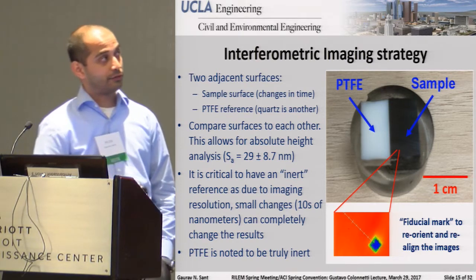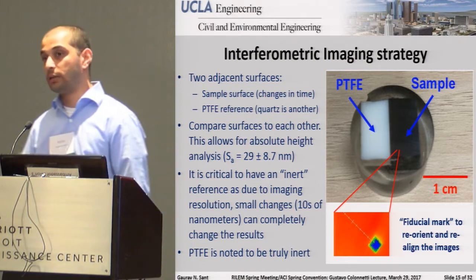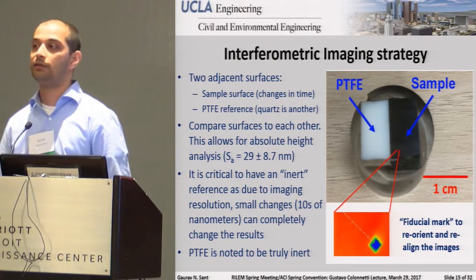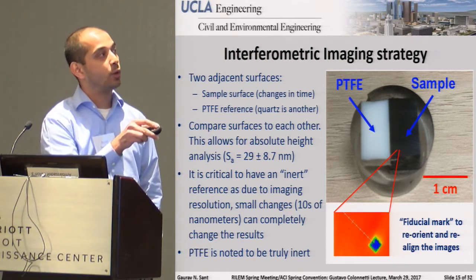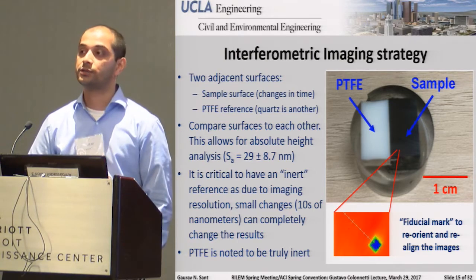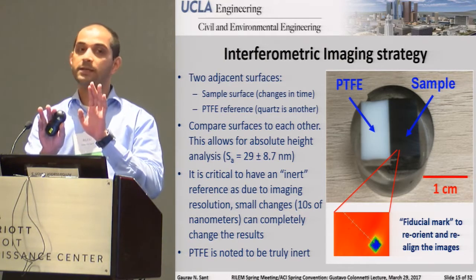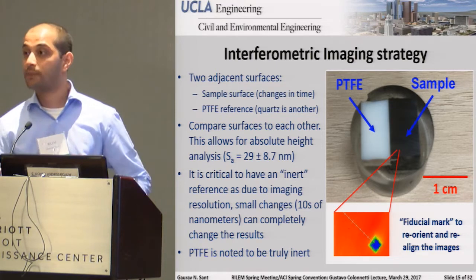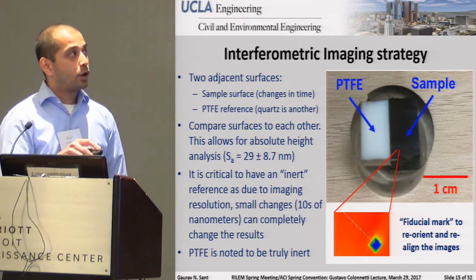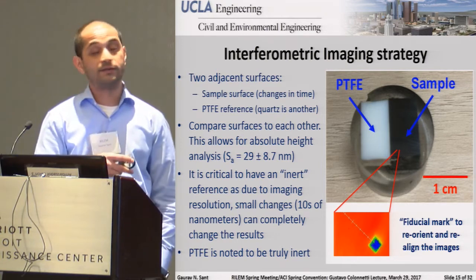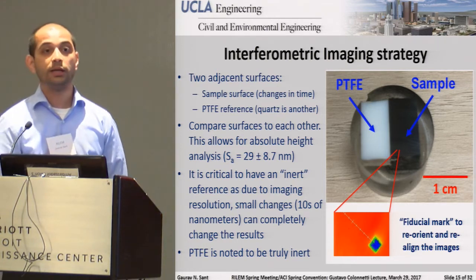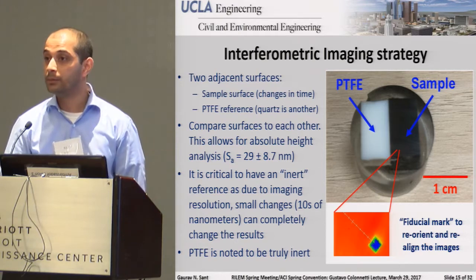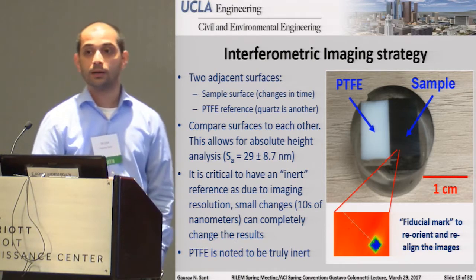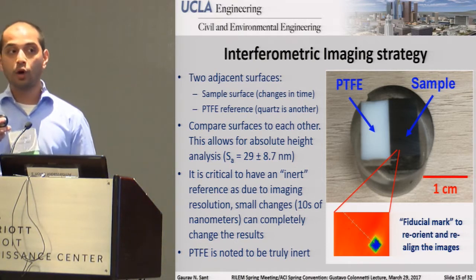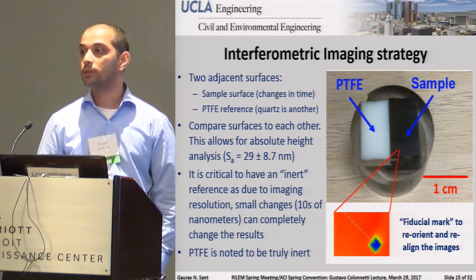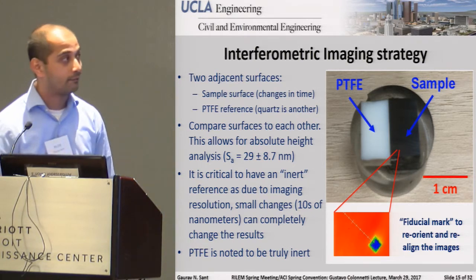Now, the reason you need an inert reference is interferometry in this manner is a relative imaging approach. So you essentially need one surface that can move and one surface that stays fixed. And based upon the relative displacement between the two surfaces, you get an indication of mass loss or mass gain. Of course, you want to be able to compare these surfaces really well. So when we've used references, we're typically using things like PTFE or synthetic diamond, which makes for pretty expensive experiments, at least in the second case. But you've got incredibly inert systems to be looking at, and that's really something that's quite important to have.